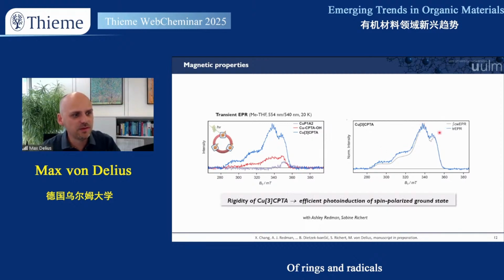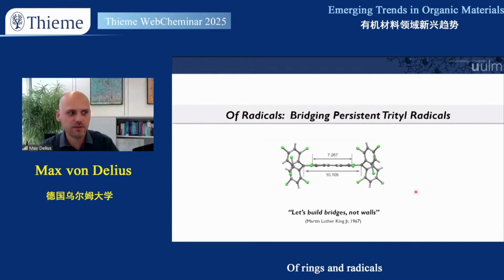So on the right, you see that the spectrum then in the end with this transient EPR is the same as if you do the traditional EPR spectrum. Only in the blue case, it has really come to life with light, with a light pulse. So this photo-induced spin polarized ground state, I believe, is something very interesting, and that we saw it now in this rigidified nanohoop, I think is a very interesting result.